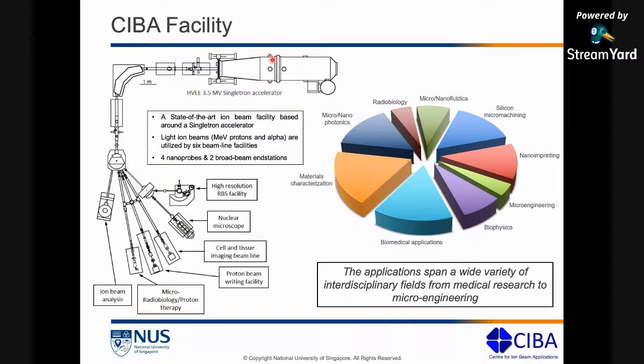When I say accelerator, what we do is we generate particles inside the accelerator and we accelerate them to high energies, typically on the order of 2 to 2.5 MeV. We work with mainly two kinds of particles, protons, which is H plus, hydrogen plus, and alpha particles, which is helium plus. We do have oxygen and nitrogen in there. So sometimes we do use oxygen ions and nitrogen ions, but our main work focuses on protons and alpha particles.